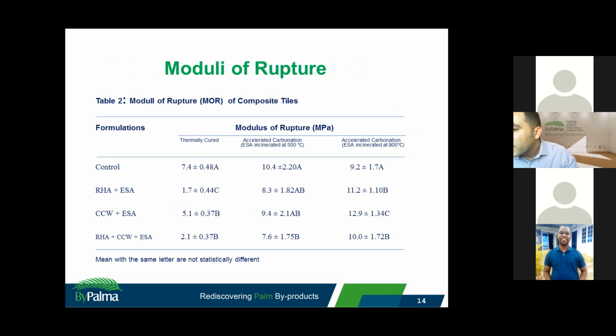Now, this is the modulus of rupture of the material. If you check from the previous slide, the rupture of the material was very low, but because of the introduction of 2 admixtures and changing the incineration temperature for the raw materials, because for all the formulations eggshell was added, because of the hydrolysis that we carried out for the eggshell. So we find out that for eggshell incinerated at 900 degrees Celsius, calcium carbide waste performs best. We have about 12.9 megapascal, which shows a good performance because of the hydrolysis.